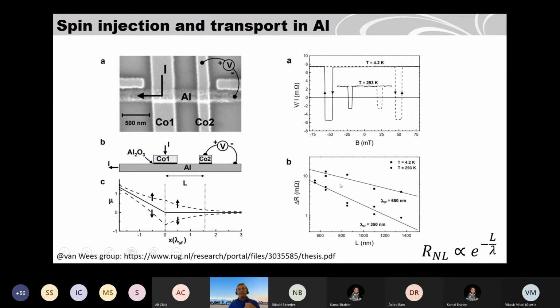So how to find the spin relaxation time in this material? You can make devices with different channel lengths, from 500 nanometer to 1.4 micrometer. This is all length in nanometer. So you can see the magnitude of the signal changes exponentially. And this is the resistance. What you see is that it depends exponentially on the length of the channel, and also on the spin diffusion length. So by fitting this equation to these data points, you can find the spin diffusion length in aluminum, which is around 600 nanometer. Okay.